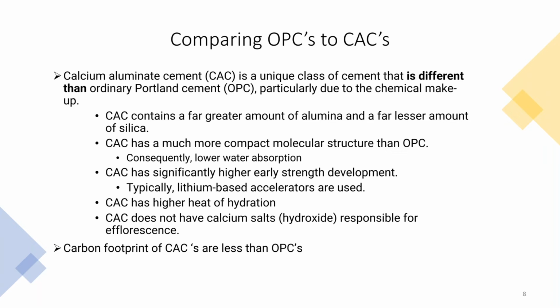And significantly higher early strength development. You'll see that if you've ever mixed a bag of our Ultracolor Plus FA, it imparts a heat of hydration, which is in the next bullet down. The bucket actually gets hot as you work through the process because of the reaction, the heat of hydration, that's causing that. It does not have any calcium salts, so no calcium hydroxide, which is the source of efflorescence. And another good point about CACs is it has a lower carbon footprint than OPCs.